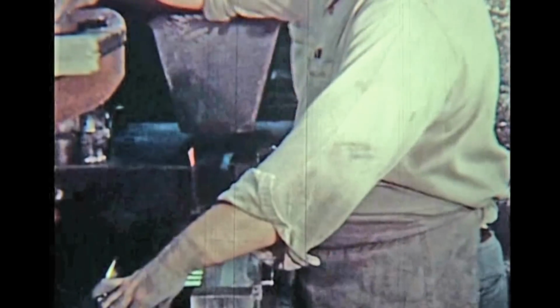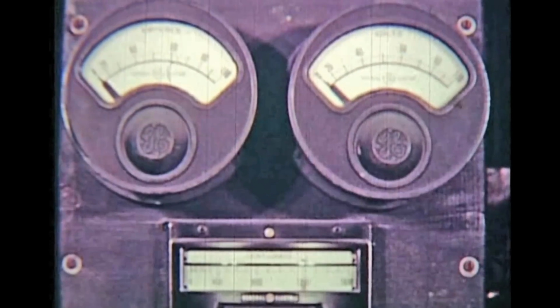The mold is disassembled, cleaned, and coated with mineral oil to prepare it for the next ingot. Note the care that is used throughout the entire pressing cycle. A molybdenum slab is used to support the ingot because it lacks sufficient strength. In addition, the ingot is pre-sintered in a furnace with a hydrogen atmosphere. After 2 hours at 1200 degrees centigrade, the ingots are strong enough to be handled as long as reasonable care is used. However, the surface can still be easily scratched, and the ingot does not have enough cohesiveness to be worked.